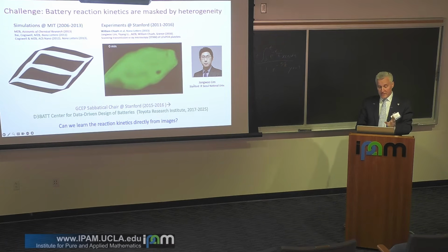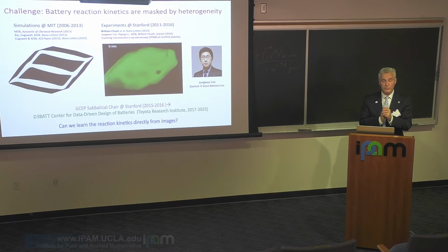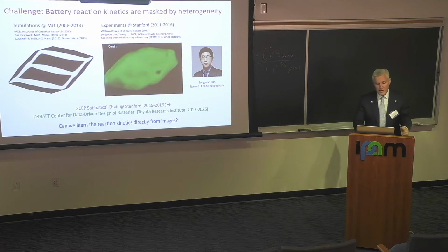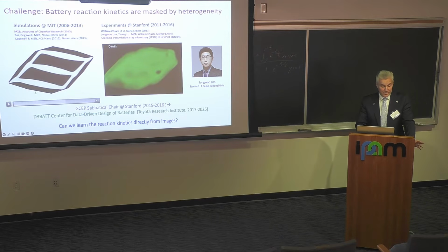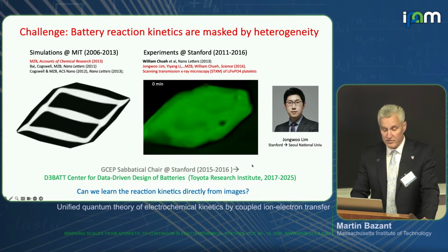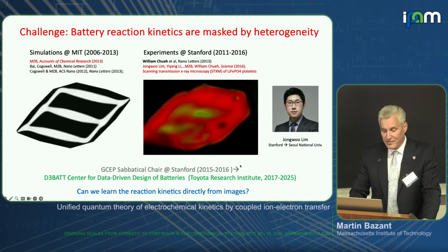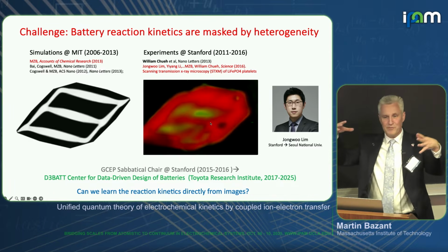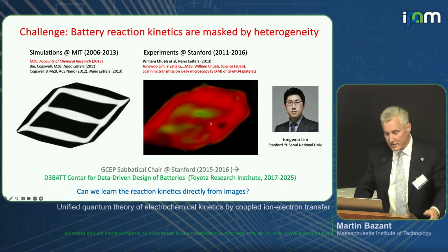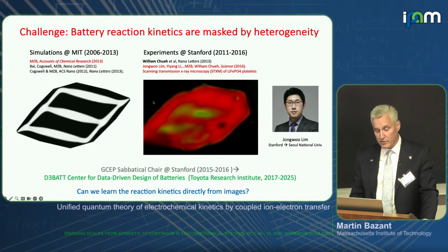The reason is that, thankfully, William Chueh at Stanford, when he was a junior faculty member, was intrigued by this and decided to use Stanford's synchrotron X-ray facilities to actually observe lithium iron phosphate nanoparticles. Jung-Woo Lim was his postdoc, who published a paper in Science with us. He's now a professor at Seoul National University. This blew me away, actually. These are actual images that they took of a particle looking like this, and keep in mind the simulation came first. It takes a little while to scan a particle. You might only get 3 or 5 or 7 images, but it's pretty striking how similar these are.